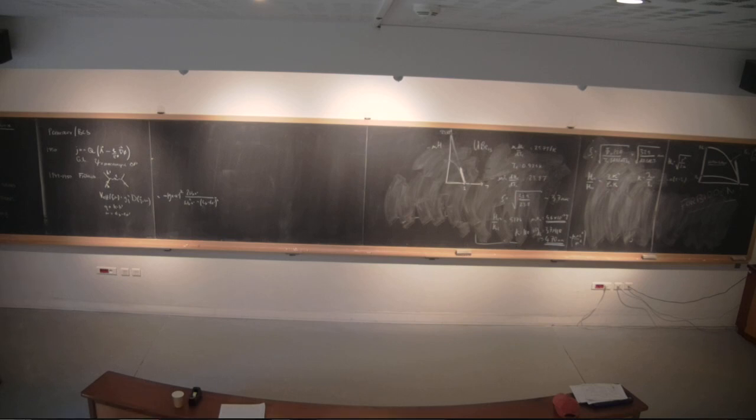Pinning is the answer. And so if you apply an electric field to a charge density wave, you have to reach a threshold field before it starts to move, okay? And that's the end of the Fröhlich theory. Nevertheless, it did lead to a fascinating prediction. It led to the prediction that Tc would be proportional to the Debye frequency, which is proportional to the square root of 1 over the mass of the nuclei. And so Fröhlich predicted there would be an isotope effect if his theory was right.